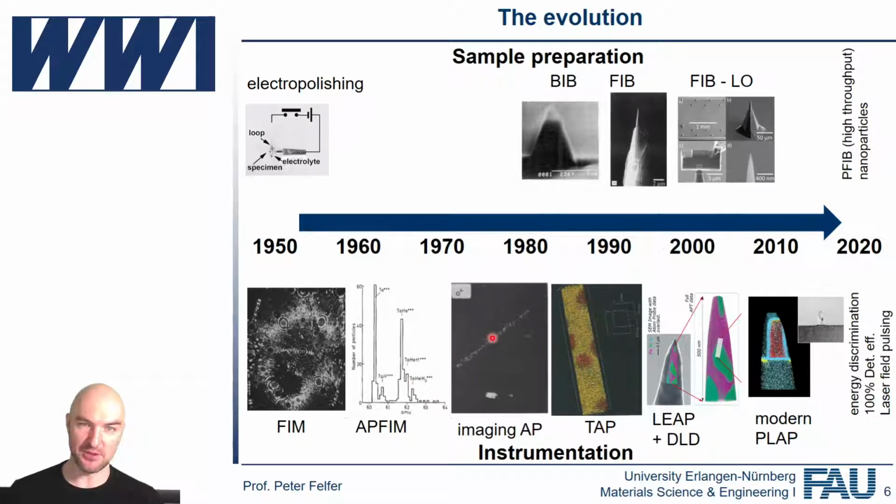So in the late 70s, early 80s, people started having spatially resolved detectors, where in the first iteration by John Panitz, you had a detector that could do 2D imaging, but you needed to pre-select the flight times you wanted to analyze. So you needed to know which species you want to look at beforehand. And you couldn't capture everything at the same time. So essentially, you got spatial resolution, but no temporal resolution. So here you got temporal resolution, but no spatial resolution, or chemical resolution, but no spatial resolution. Here you got spatial resolution on a fixed chemical resolution.